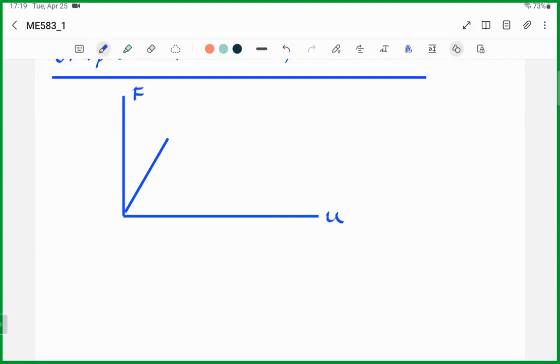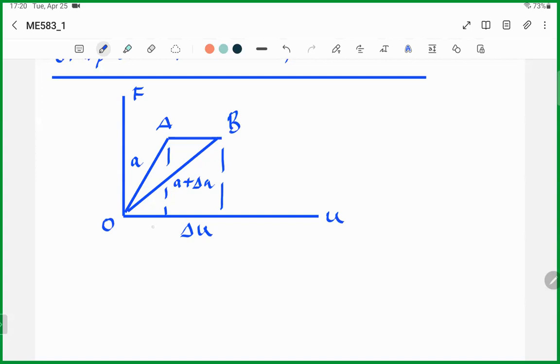Now I suppose that crack propagation started, but now that we have a control on force and we are keeping it as constant for this crack propagation direction. And at the end or in the next stage, there is going to be a new crack length and lower stiffness in the specimen, so that at this initial point, crack length is A, and at the final configuration, crack length is A plus delta A. And there's a certain amount of delta u here in the specimen. And I'm going to label these points as O, A, B, C, and D. This crack propagation direction.